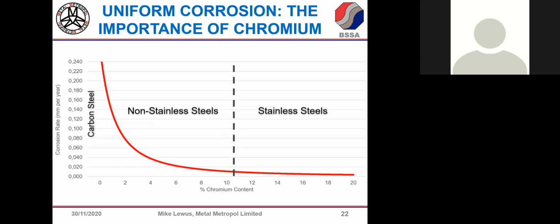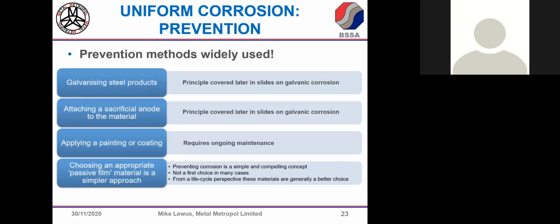It tends to only be a factor when the material's been exposed to really aggressive chemicals like concentrated sulfuric acid or something like that. So obviously we're well away from that. We don't really have to worry about uniform corrosion. The thing we have to be concerned about is localized corrosion mechanisms. You'll be familiar with ways of preventing uniform corrosion. You might actually choose a stainless steel to avoid it. The bottom line on here: choose an appropriate passive film material. Other ways are using something like galvanized steel or sacrificial anodes or painting or use of coatings.